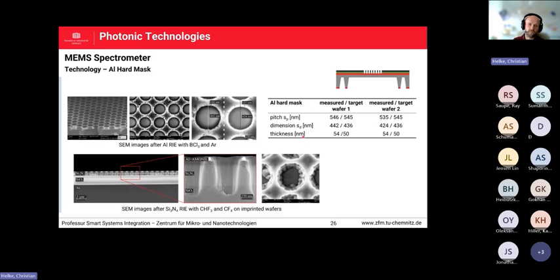So first of all, we have to open the aluminum hard mask, and in different wafers, we test different process parameters, and this had an influence on the pattern fidelity of course. So for example, you can see it here on the left side. On this wafer, we use this process which ends up in a 442 nanometer circle hole diameter, whereas on the right side, it's another wafer. We ended up with 424 nanometer, for example. The aim was here to get 436 nanometer. So we have one above and one below, but it looks really promising.